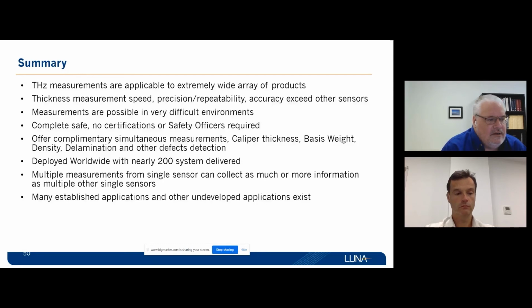And we can measure not only thickness, but if you're doing imaging, you can then see defects and delaminations, or map the thickness if you want. So it can also look inside the coating to see bubbles, or look on the substrate for rust, or if it's just a thin sheet of material, or something like a radome that's meant to transmit all the way through, then you can inspect the entire interior of the radome.